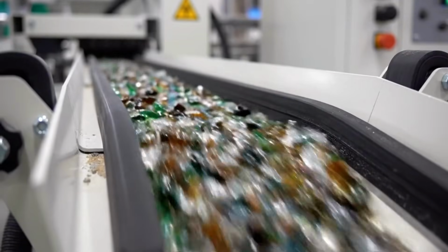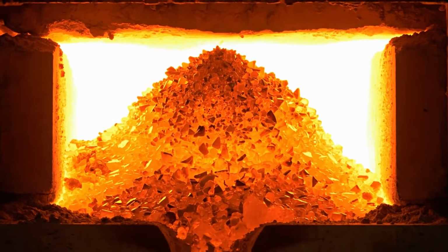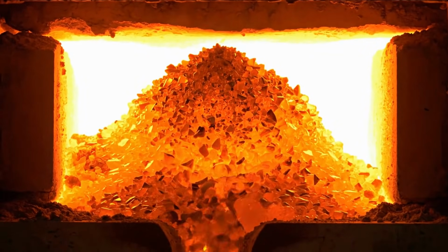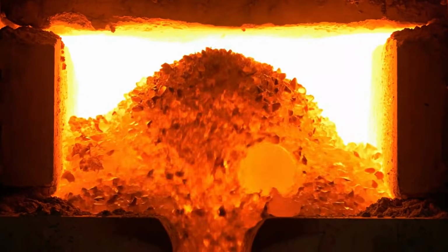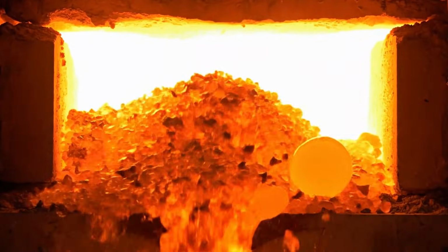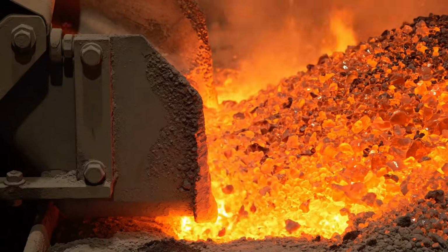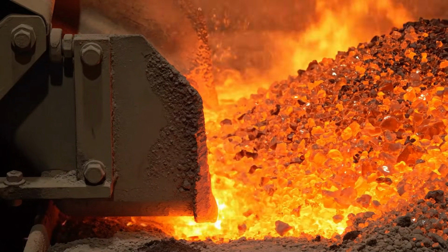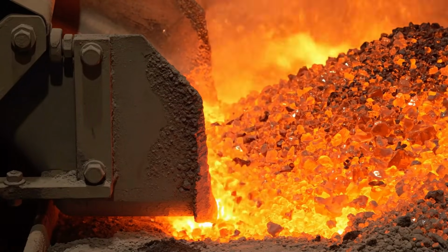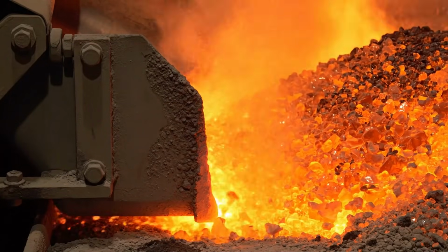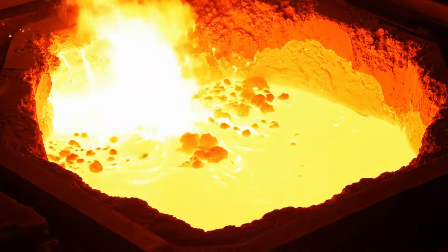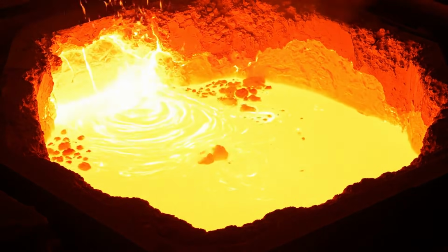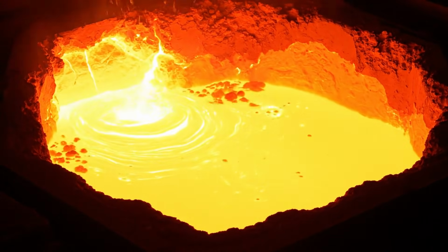Scientific benefit. Cullet melts at lower temperatures than raw materials. Using cullet can reduce energy consumption by up to 40% compared to manufacturing glass from virgin materials like silica sand and limestone. This happens because the molecular bonds in glass have already been formed. Reheating simply returns the material to its molten state without requiring the complete chemical transformation needed for raw materials.